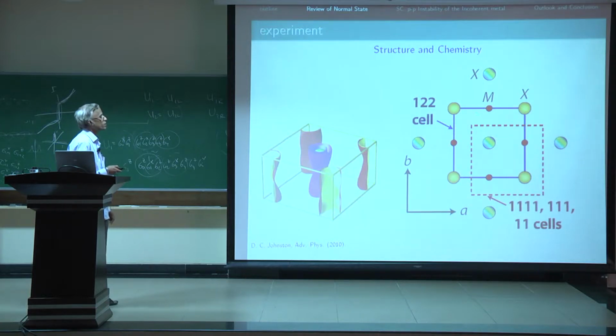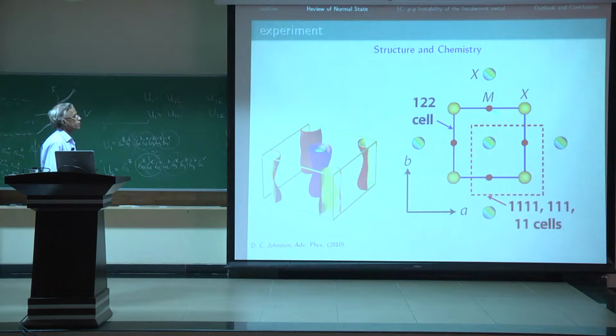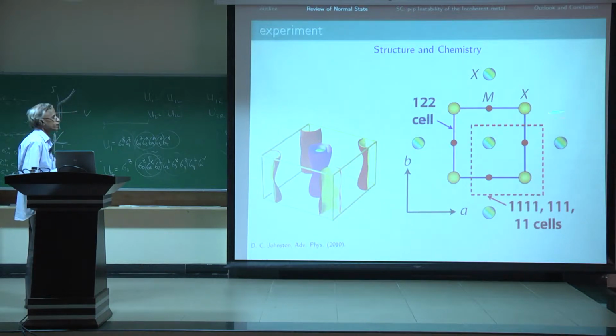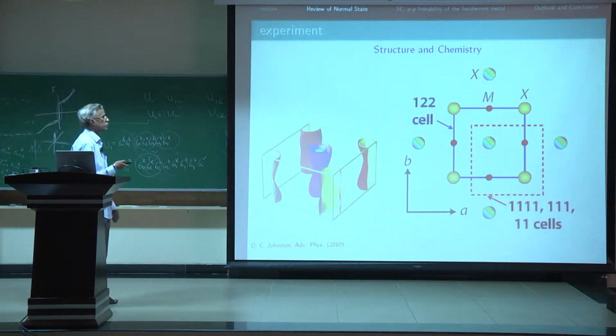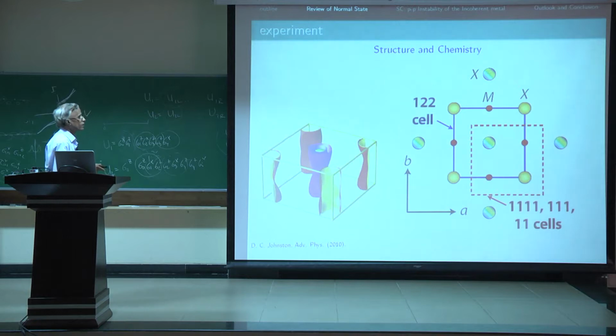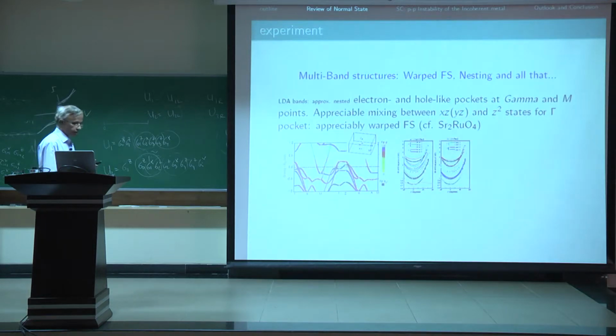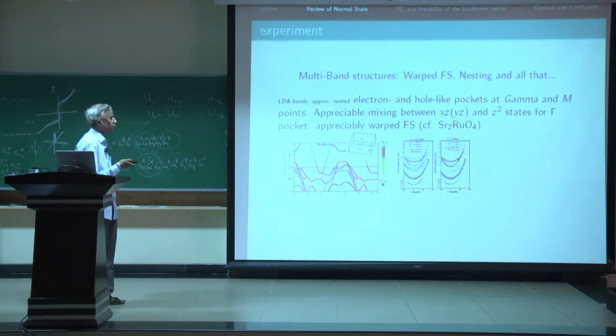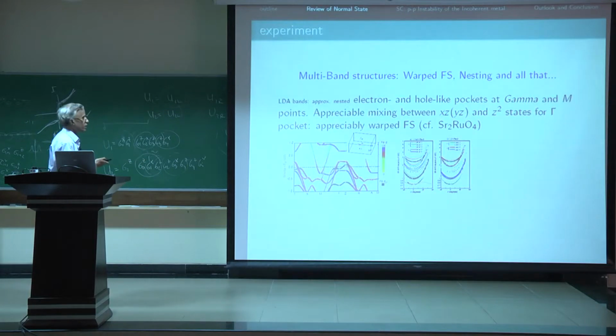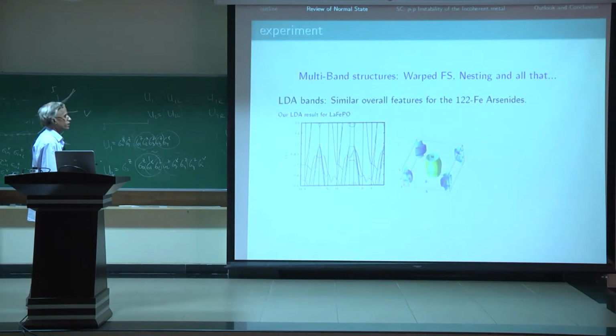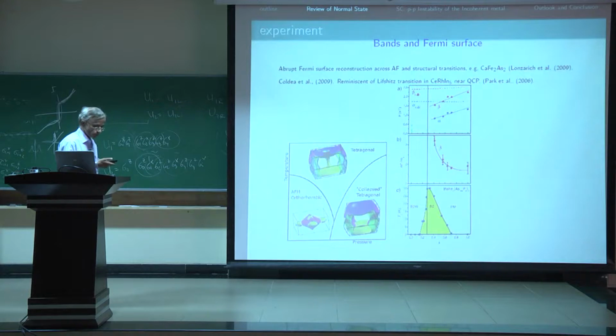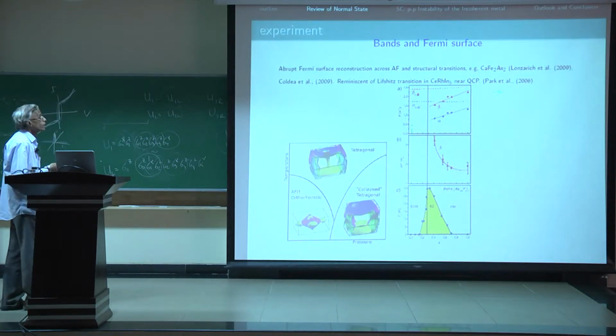So the direct d-d hopping is actually modulated by hybridization with the arsenic p states, and the diagonal hopping is actually of the same order as the nearest neighbor hopping on an effective square lattice. That implies a large frustration in an effective J1, J2 picture in a strong coupling limit. One would naturally expect stripe antiferromagnetic states, and these are precisely what are observed. Okay, so